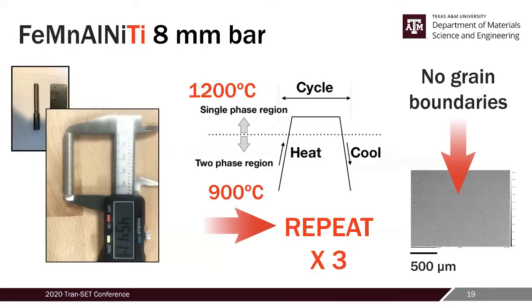And in the iron manganese aluminum nickel titanium 8 millimeter bar, after cycling this material 3 times between 900 C and 1200 degrees C, you can get large grains. We didn't observe any grain boundaries after these heat treatments. Still, we are continuing this work.